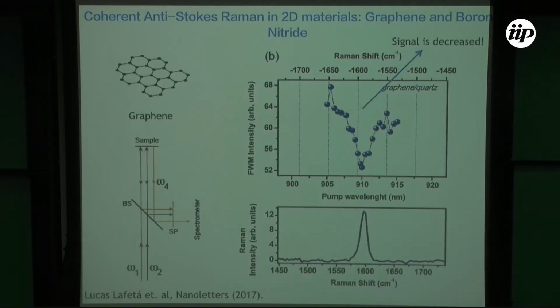And then we did the same kind of experiment in graphene. In graphene, what happens is that you have very strong four-wave mixing, but when we tune the difference of the laser energies to the Raman peak of graphene, that's the G band, instead of observing enhancement of the signal, you just observe a decrease of the signal.